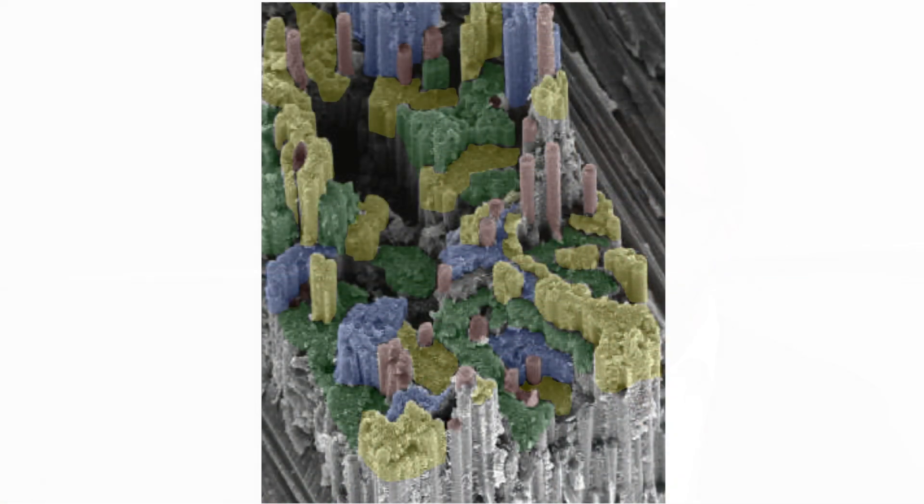We then looked back at translaminar fractured surfaces in cross-ply laminates and noticed that there too there were several scales in the fracture surface. One implication of this is that in larger bundles or in thicker zero-degree ply blocks more scales can be fitted.